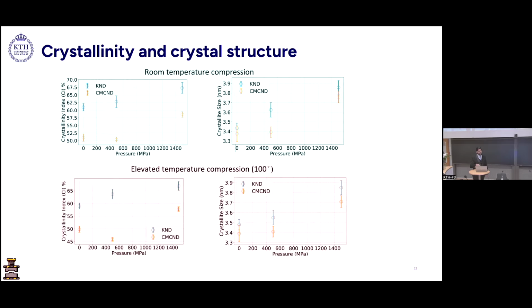So we wanted to see how the crystallinity and crystal structure look. We did the crystallinity analysis, and as expected, Kraft pulp showed higher crystallinity as we increased the applied pressure. From 0 to 1500 megapascals, it showed a continuous increment, and the crystallite size was getting higher. In the case of carboxymethylated pulp at room temperature, we hardly saw any increment in crystallinity at 500 megapascals, but at 1500 megapascals we saw a little bit of increment. At elevated temperature, the carboxymethylated pulp actually showed a little less crystallinity at 500 megapascals, and again it went a little higher at 1500 megapascals.